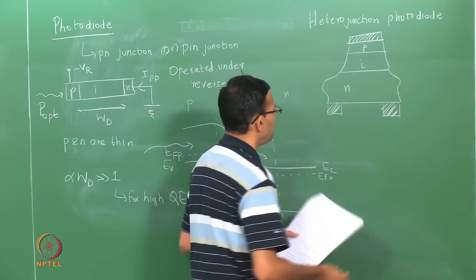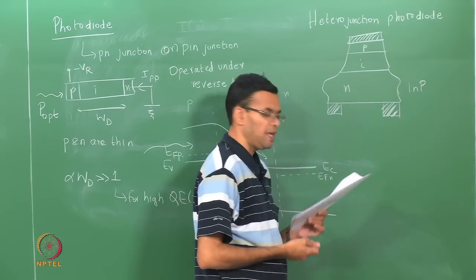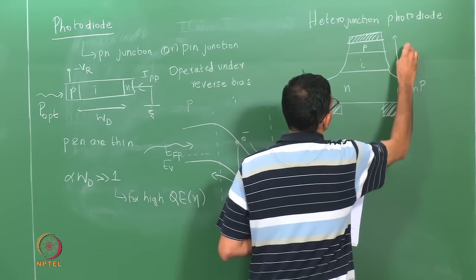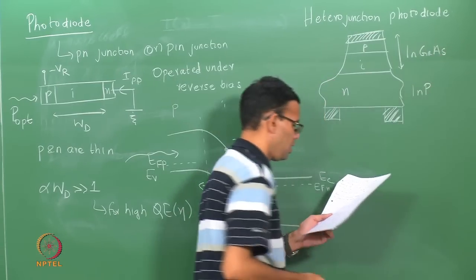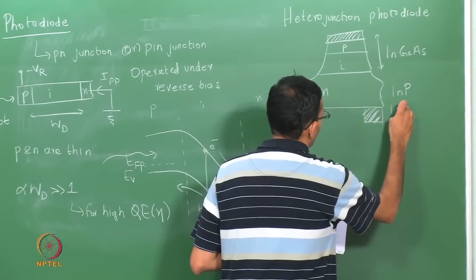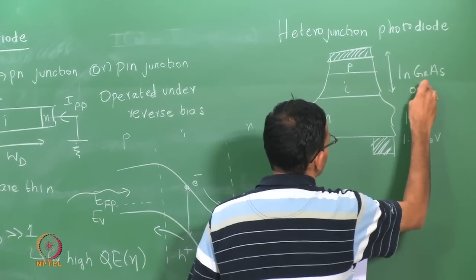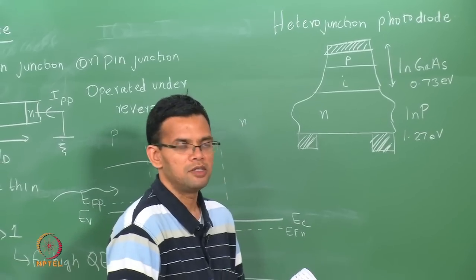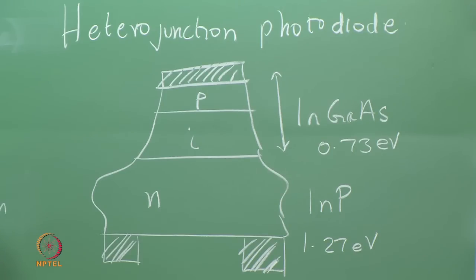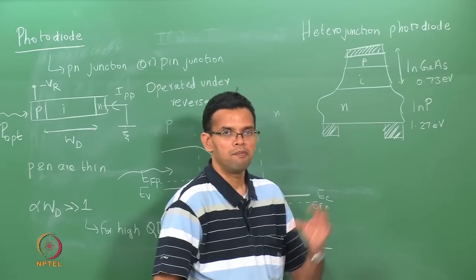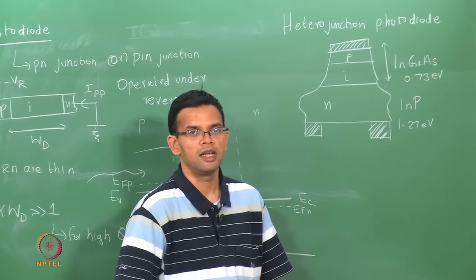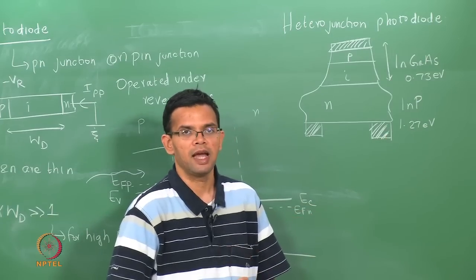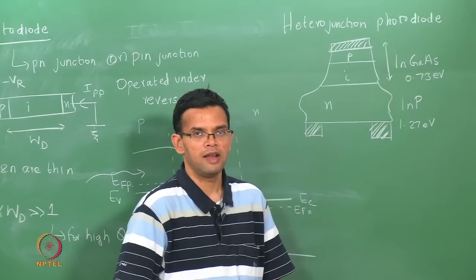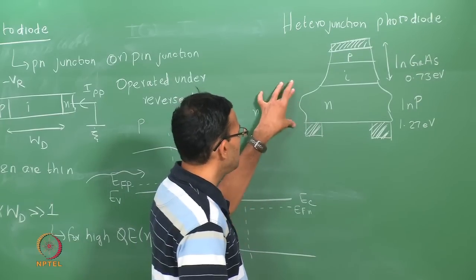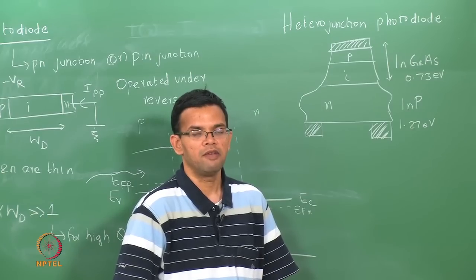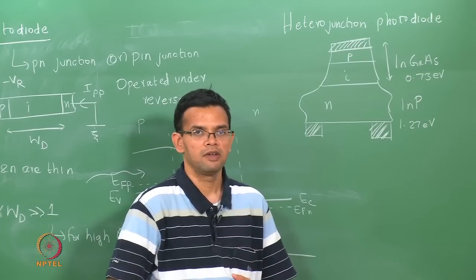So, my N region is made of indium phosphide and my P and the intrinsic regions are made of indium gallium arsenide. So, indium phosphide has a higher band gap, 1.27 eV, and indium gallium arsenide has a band gap of 0.73 eV. The advantage of the heterojunction device is that in the case of a regular PIN, the P and the N regions should be really short in order to not absorb the light. But here, since indium phosphide has a higher band gap, wavelength whose energy is less than this will have very little absorption in the indium phosphide, so that the thickness of the N layer does not have to depend upon the wavelength of the light. You can have a thicker N layer than what you normally have in a regular PIN device.